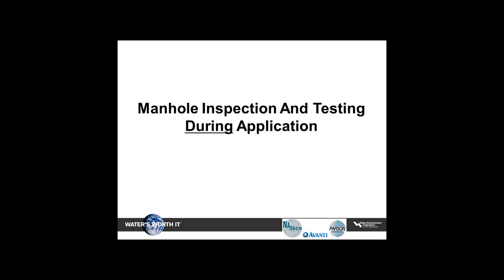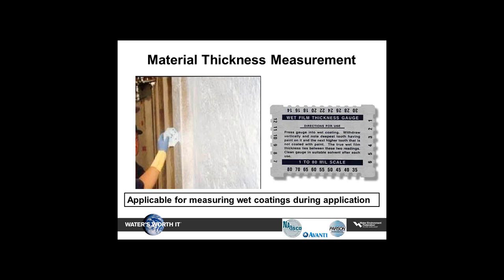And during manhole application, there are some inspection methods that we can look at. Your material thickness can be measured during the actual application. This is typically applicable to a product that doesn't set up very quickly, such as an epoxy. The gauge has different depth gauges on it that the applicator can actually penetrate into the wall of the coating and give the inspector a reading at any point during the application of what the thickness of that coating is.